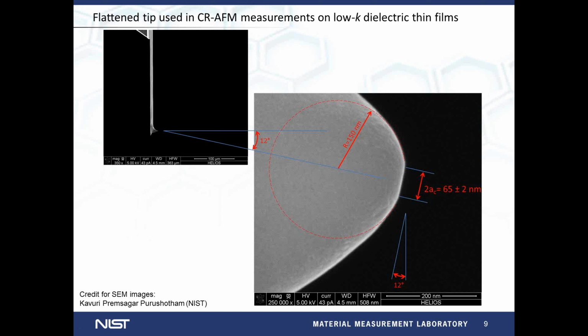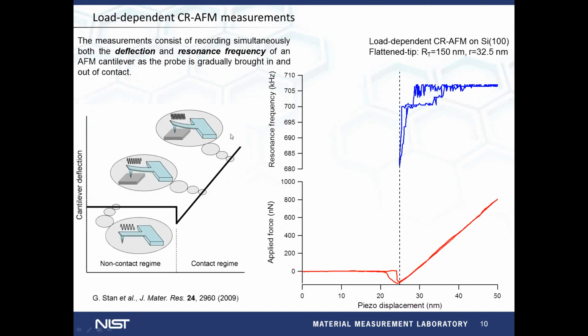We were sure that no extra flattening was produced during measurements, so the probe was actually behaving as a circular flat punch. The flat here is produced at about 12 degrees with respect to the cantilever orientation due to the tilt of the cantilever in the holder. With such a flattened probe, we performed load-dependent CR-AFM measurements, which consisted of recording simultaneously both the deflection and resonance frequency of an AFM cantilever as this is brought gradually in and out of contact.